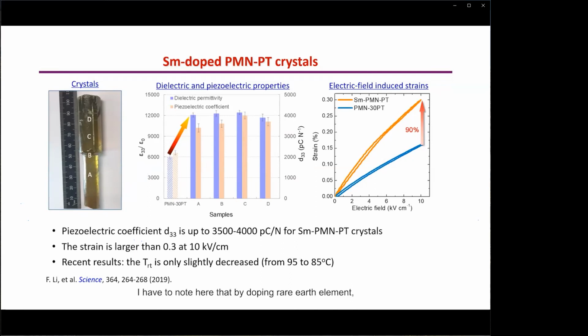I have to note here that by doping rare earth elements, the phase transition temperature TRT will be decreased. In the paper published in Science, the TRT is only 95 degrees centigrade. Well, by carefully tuning the composition, at present we can have samarium-doped PMN-PT crystals with TRT of 85 degrees centigrade, and the d33 is still around 4,000 pC/N.